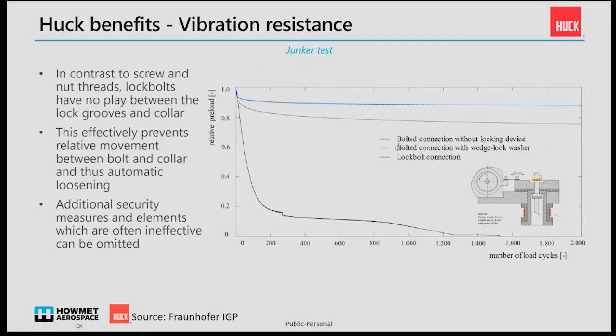And a Lockbolt does give you the highest vibration resistance. The blue curve is a conventional lockbolt installed into a shear joint, and you see only very little loss of preload in the initial stages of the test. This is due to some embedding of the collar and the pin head into the components. But after that, there's almost no loss of preload, even after 2000 cycles.